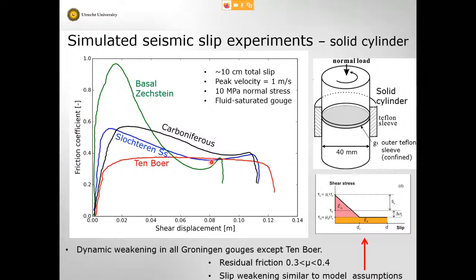The sandstone also shows a substantial drop. So does the Carboniferous material, the Tubbergen, less so. Now, these all exhibit some sort of slip weakening behavior after a peak strength. This type of behavior is capable of producing an earthquake because you have a drop in strength, which means you can get acceleration under a given load in a given elastic loading system. So this suggests very strongly that the basal Zechstein would be very sensitive to earthquakes, the Slochteren too, and perhaps the Carboniferous. These are preliminary results. We have to repeat these experiments because there are some discrepancies.